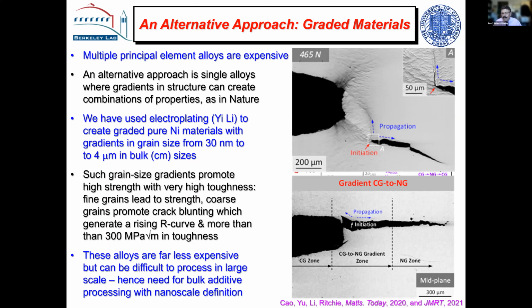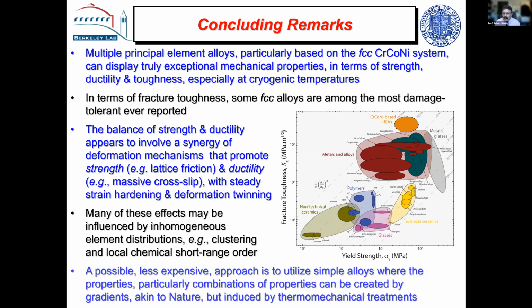just with a simple nickel material, very simple. So let me conclude, but I've tried to look at some of the various ways to make high toughness, high strength materials, and that's what damage tolerance is. It's making high toughness without degrading the ductility. I gave some examples from steels and bulk metallic glasses because they're very different. But in these high entropy alloys, the FCC materials tend to be, I think, the toughest materials we've seen.